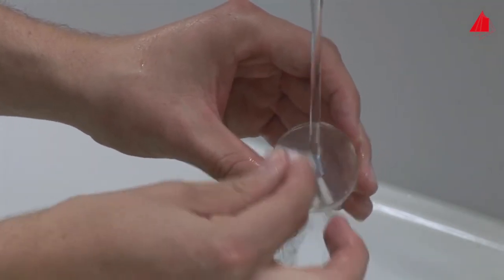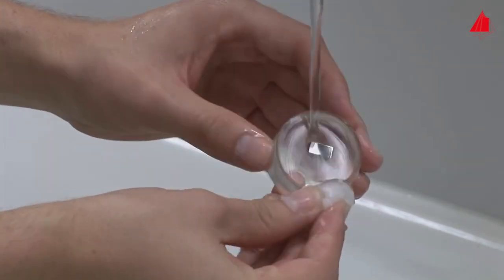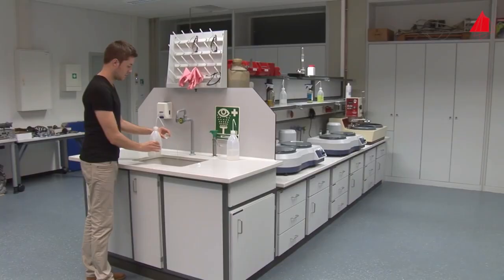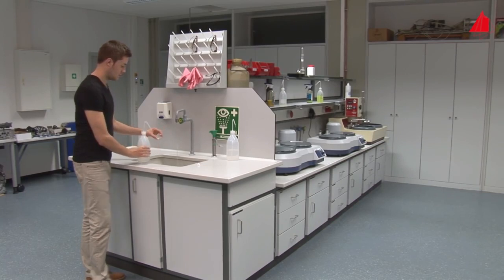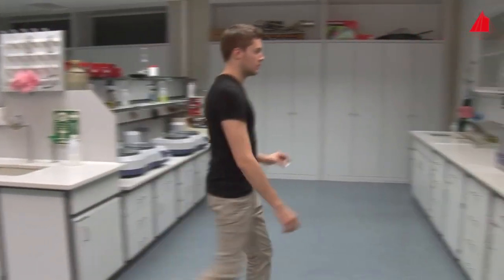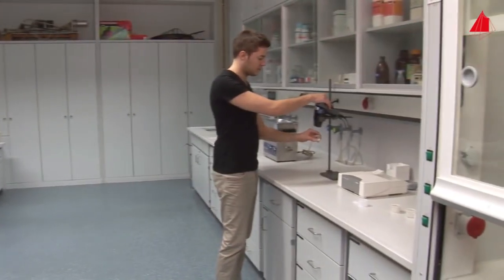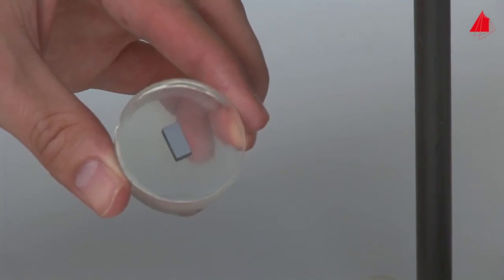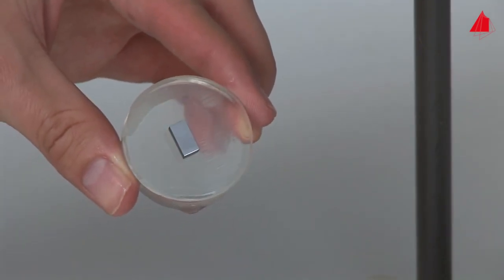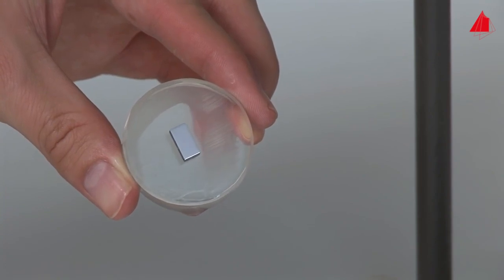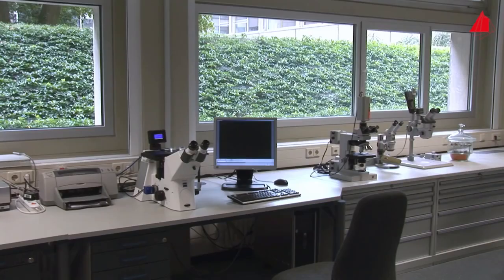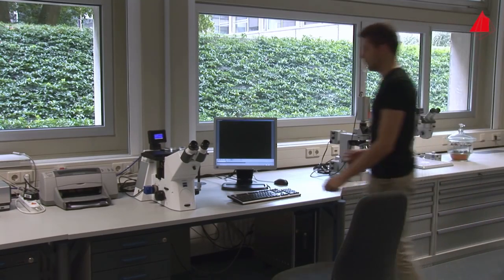Under running water, the material tester gently wipes the specimen with cotton wool, thoroughly rinses it with alcohol, and dries it with a hairdryer. From now on, the sample is called a metallographic specimen or microsection. Judged with a naked eye, our metallographic specimen seems to be well prepared. It is now allowed to go under the microscope for the first time, or rather onto the microscope.